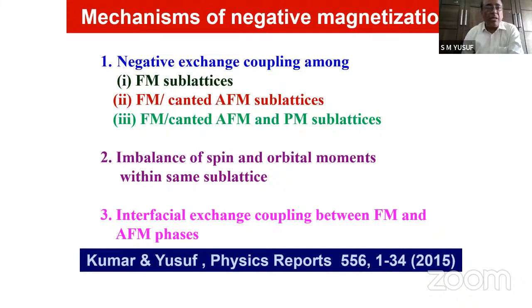but if there is a negative exchange coupling among two ferromagnetic sublattices, or ferromagnetic, canted antiferromagnetic, or paramagnetic sublattices, then you would expect imbalance of spin and orbital moment can also give this kind of magnetization reversal. Interfacial exchange coupling between ferromagnetic and antiferromagnetic phases also can give it, which so far we have studied in all bulk material, and in one nanoparticle case, I showed you that the interface is formed due to core and surface disorder, and that gives it.